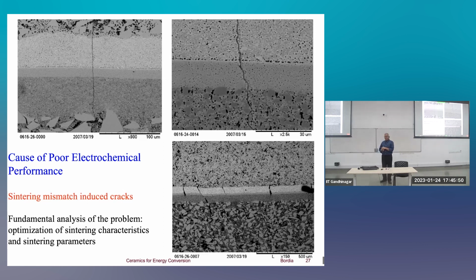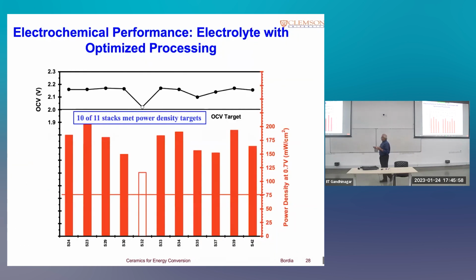So we worked on this with them, went through their processing route step by step, and were able to actually fix it. And then they were able to make these fuel cells in which all of them, with this modified processing, a classical material science kind of approach, were able to meet both their power and their open circuit voltage requirements. A significant improvement, but it took, again, 2 years of very careful materials research to find out which steps they could change and what impact they would have. But it's a successful project that they were able to implement.